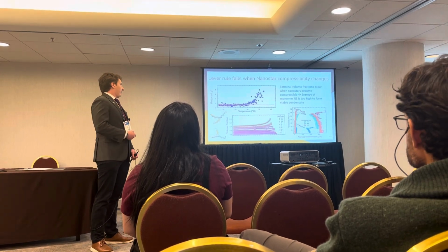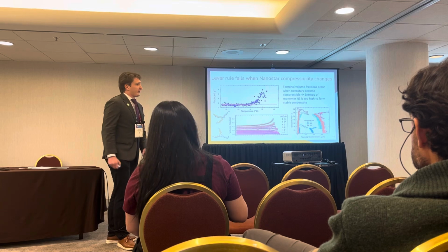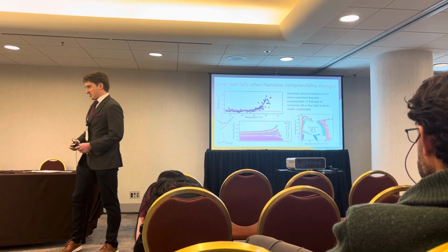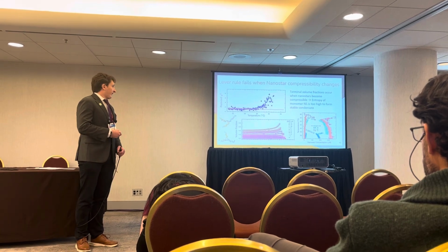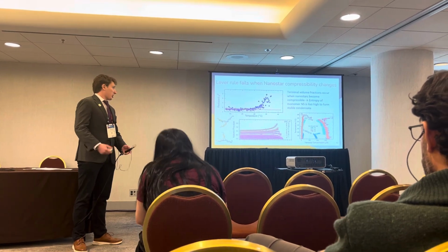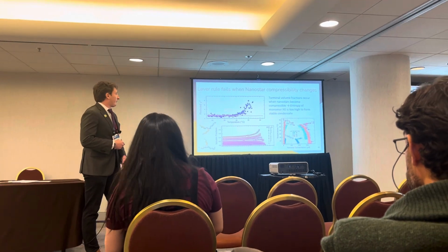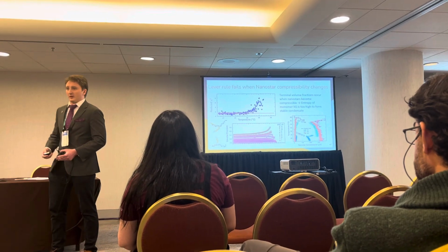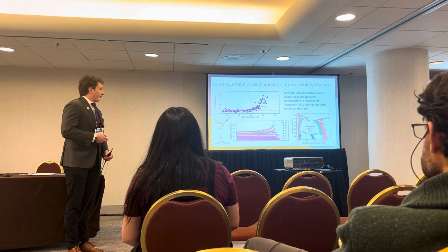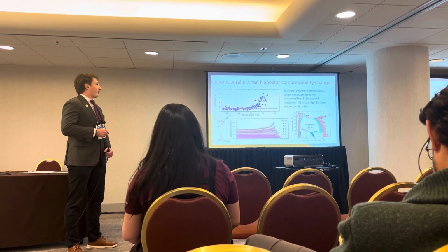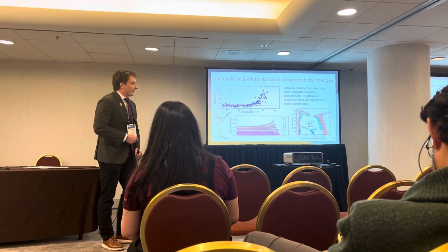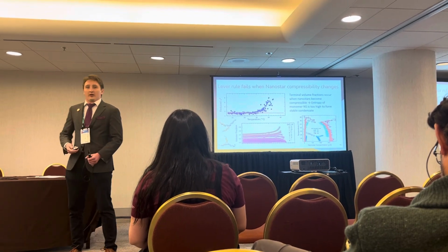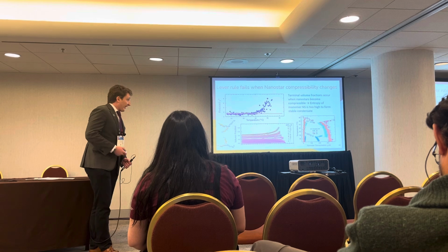What's the result of this? Well, we've already said that at low temperature, we're able to get a linear scaling relationship between volume fraction and concentration. This is likely due to the fact that the hybridization interactions are very strong in the system at low temperature. And we don't really see these minor differences in flexibility manifest in the scaling relationship. But as we hamper the ability for the sticky ends to hybridize transiently, as we go up in temperature, these finite differences to the entropy of the monomer begin to matter more and more. And the lever rule as a model completely breaks down.